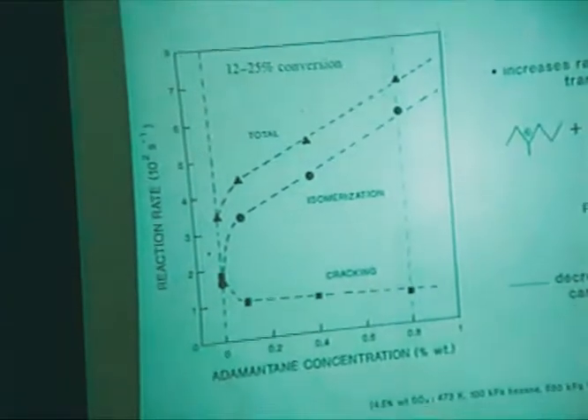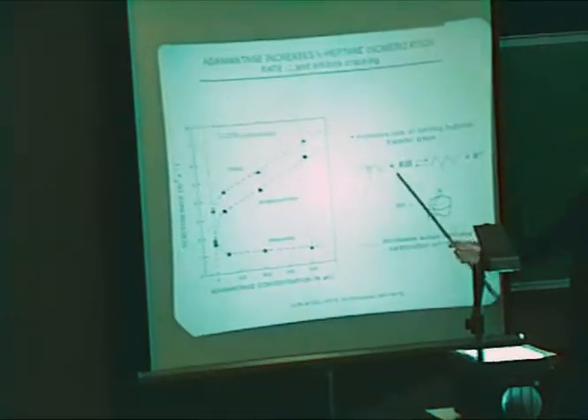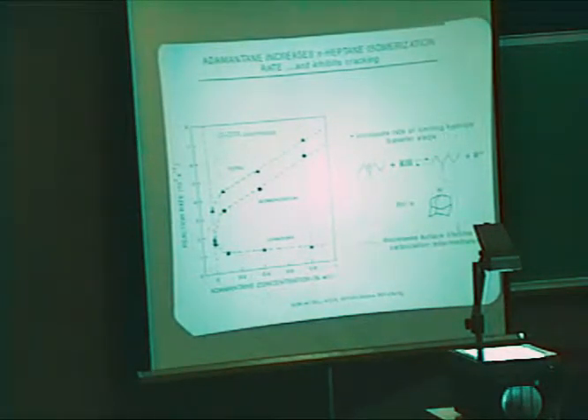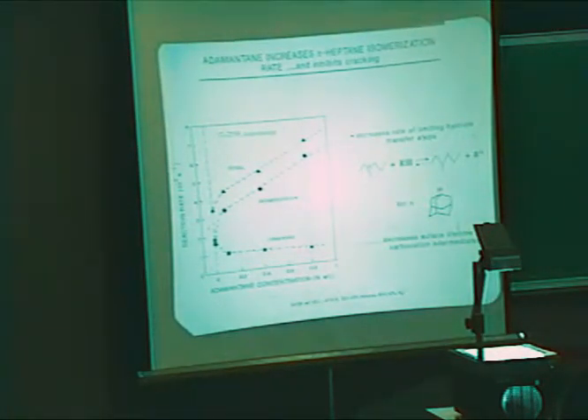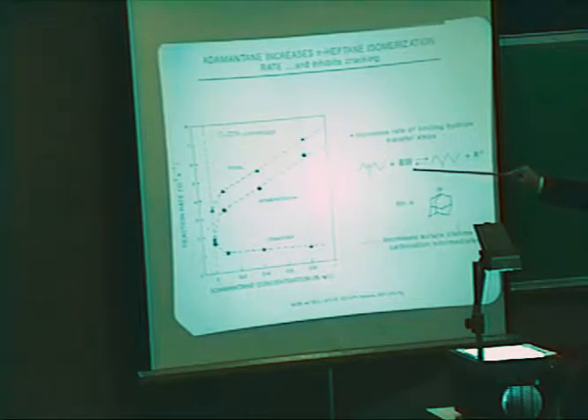And with the help of George Kramer, who had done a great deal of work in this area, we actually came up with something that is not an inorganic catalyst, but actually an organic co-catalyst for this reaction. There's a molecule called adamantane that has four identical hydrogens. It is a very unreactive molecule, except it will form a carbocation by transferring one of these hydrides, and then it will regenerate itself again and again. It's a rather expensive molecule. Now the question is, how effective is it compared to this species that you already have in the system that are doing that hydride transfer reaction? Well, if it's more effective than those species, we ought to get an increase in the rate and a decrease in the cracking selectivity as a result of having that hydride transfer agent there.